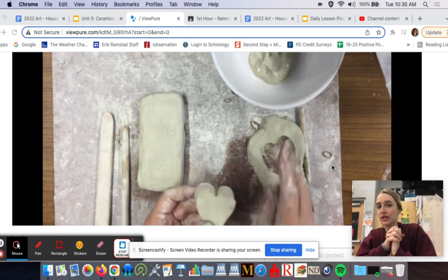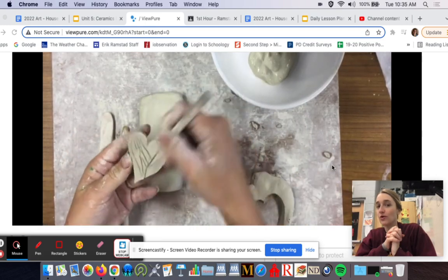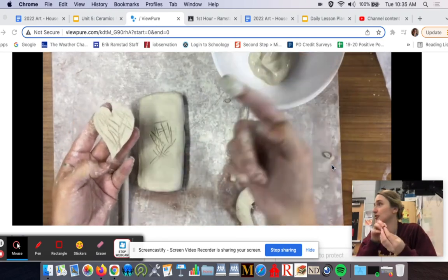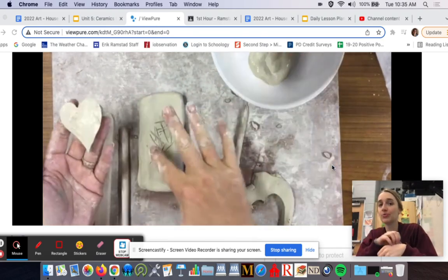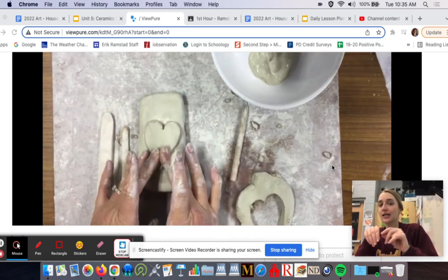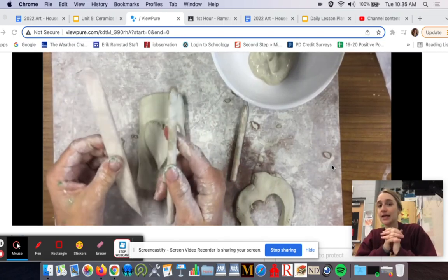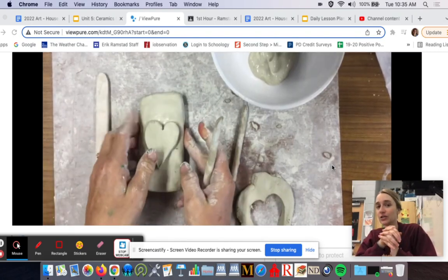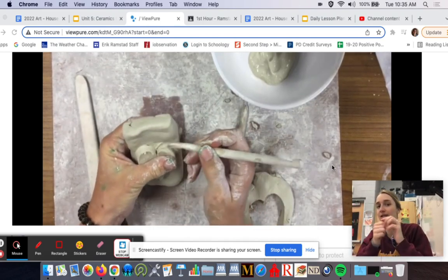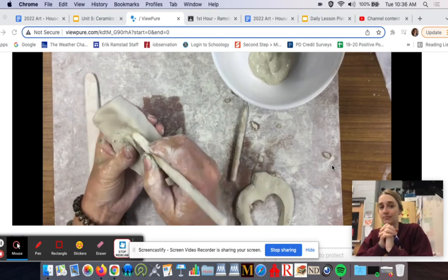It's going to smooth it out just a little bit. And in order to attach the clay, she has to score first. So scoring means just scratching up the surface of both where you're going to attach to and what you're attaching. Okay. Then you take slip, which is basically watered down clay or water, okay, straight up water, and you're using that as like the pottery glue to stick the 2 pieces together. Okay. Then the next step is blending. So you're taking a modeling tool or your finger and you're mushing or blending the 2 pieces of clay together so they're actually welded together.